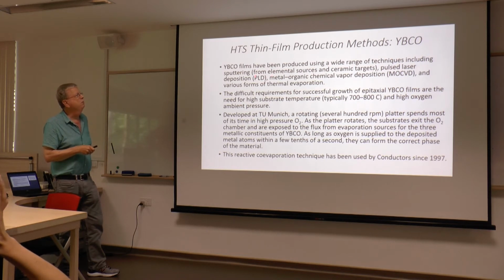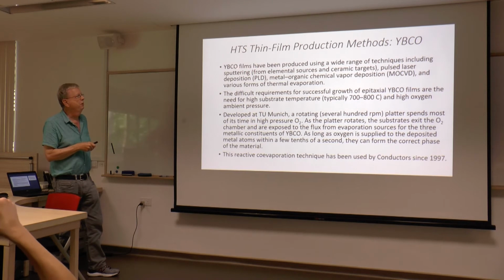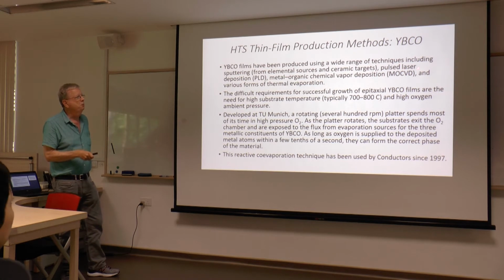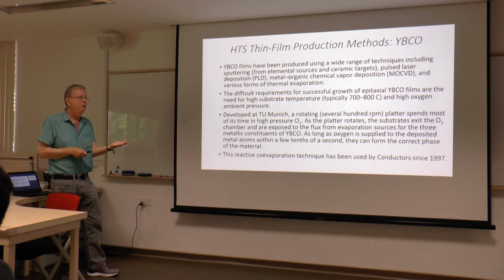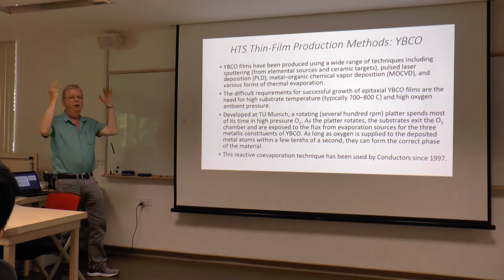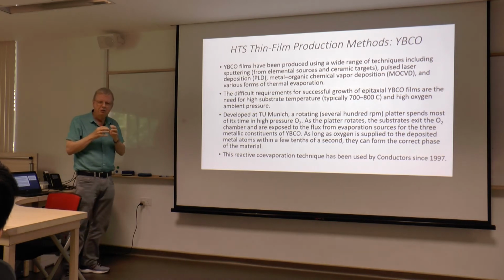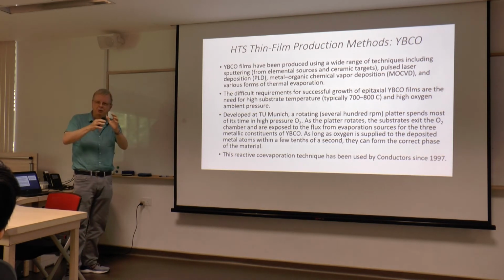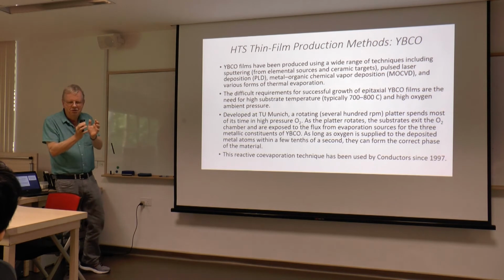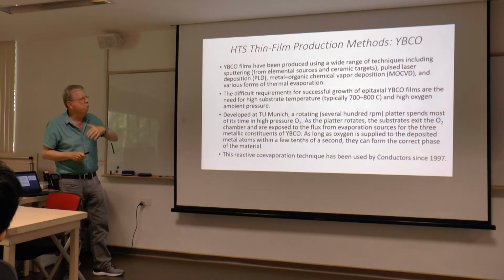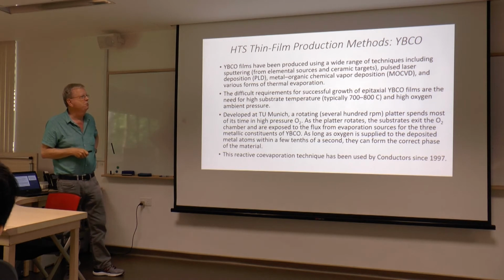So one of the methods for making materials, whether it be a high temperature superconductor film or something else, that I've always found very interesting is pulsed laser deposition, or PLD. You take a target of whatever it is you want to make a film out of, and you blast it with a laser pulse, which means you blow off physically, not atomic material, but pieces of the material that are actually larger than a unit cell. They're actually physically larger in extent, not just atomic size, and you blow these pieces down on a substrate, which if you heat the substrate, you can manage to have these pieces form a rather nice film together.